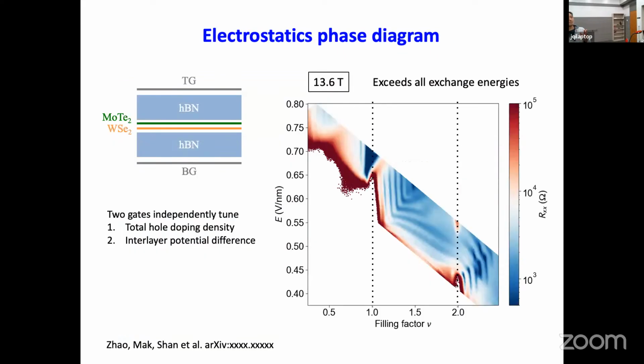And actually, I can show you the data immediately. So this is the data at 13.6 Tesla. We just apply a very large magnetic field so that we can see the Landau levels. The magnetic field will exceed all exchange energy scales so that we can clearly see all the Landau levels developed. So you can see that this is filling factor 1, this is filling factor 2. You can see the development of the vertical stripes, which is only from the Landau level of the tungsten layer. And it's independent of the electric field, which just shows that we are